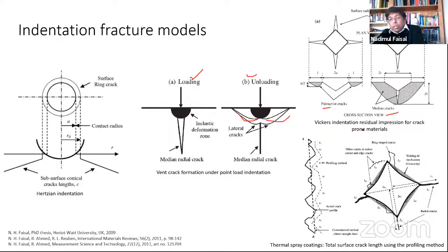And then during my research thesis, I was working on thermal spray. Thermal spray will not fracture the way glass or ceramic material fails. In thermal spray coating, there are a lot of edge cracks and other smaller cracks, which you can't compare with the standard models. So that required a different way of measuring cracks, where you measure those cracks using a microscope or some imaging technique. This zigzag length will be higher than the straight path. So if you use a straight path mechanism to measure crack length, you are actually underestimating the fracture toughness values.